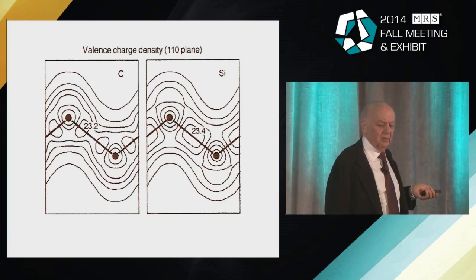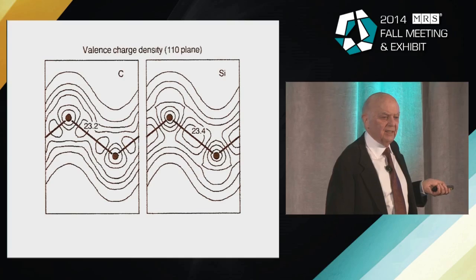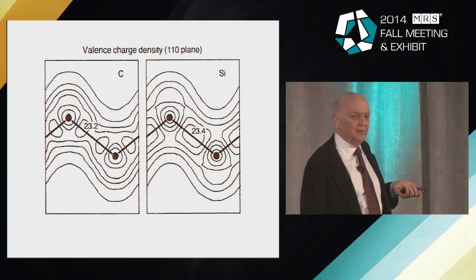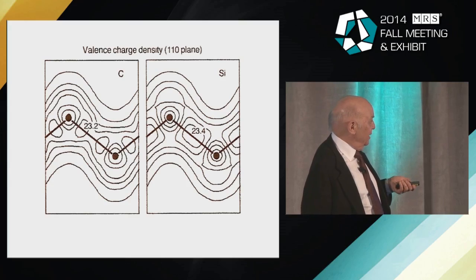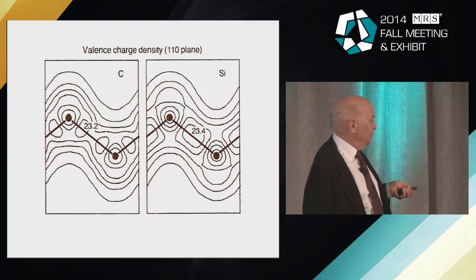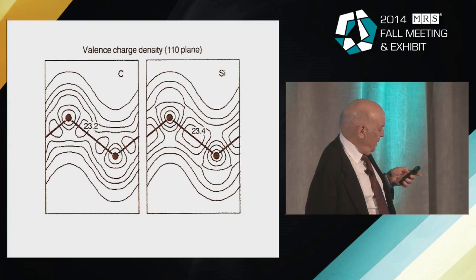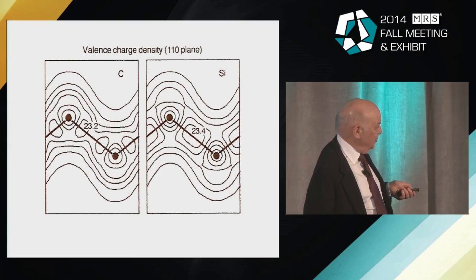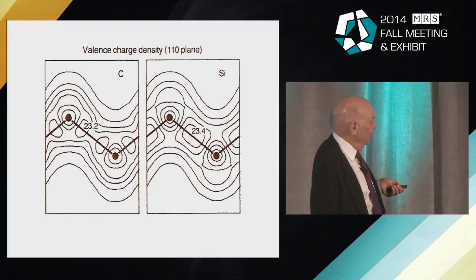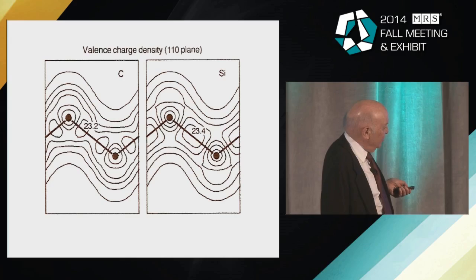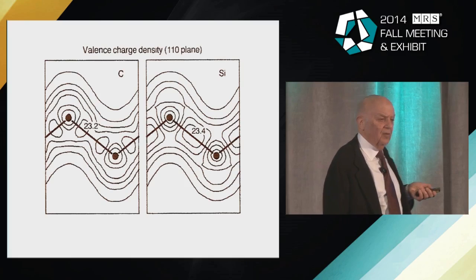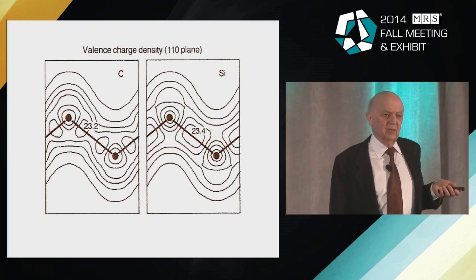And that turns out to be important. In fact, it's fundamentally associated with the concept of why you're alive. People say silicon is the basis of geology and carbon is the basis of biology, and it's because of this. In silicon, there are electrons in the core, p electrons, angular momentum 1, that push the charge into the bond. Carbon, which is in the first row of the periodic table, has no p electrons in the core, and so it doesn't push them out. So this is a double hump charge. And so carbon can form multiple bonds and make all those nice biological molecules.